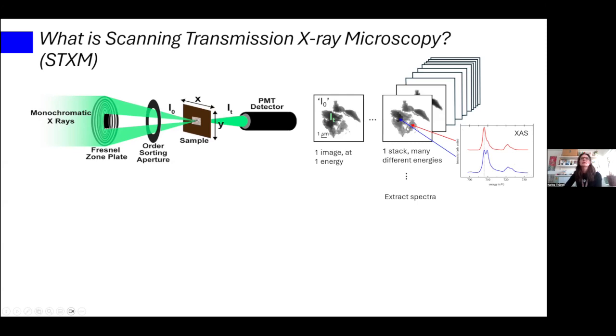And not only that, if you see that in your stack of images, there are certain areas that behave slightly differently than other areas, you can pick those together in the data analysis program afterwards and say, okay, give me the spectrum over all of these pixels, over all of these energies, and tell me what it looks like. If you then indeed search for areas that look similar, then you can map out different spectra.